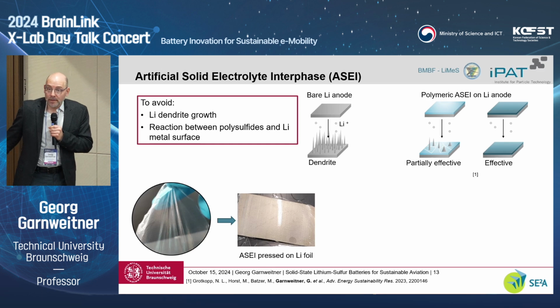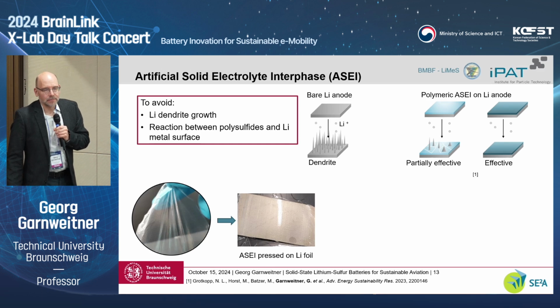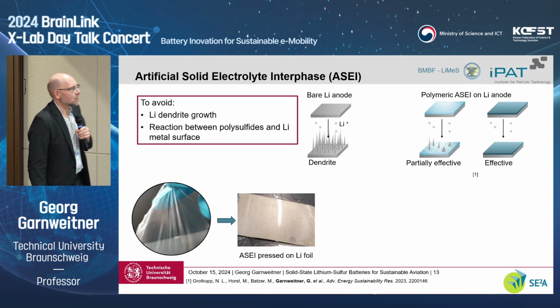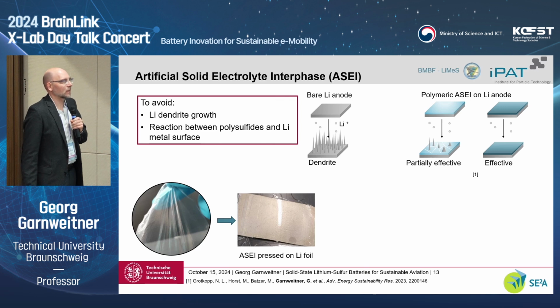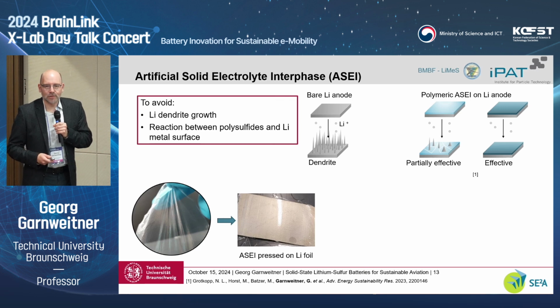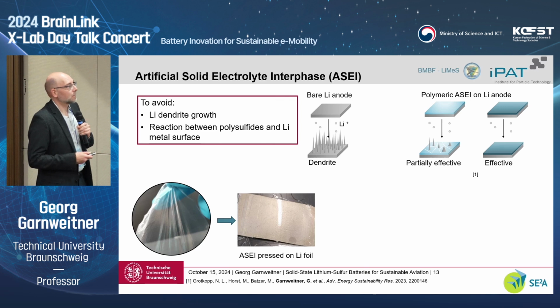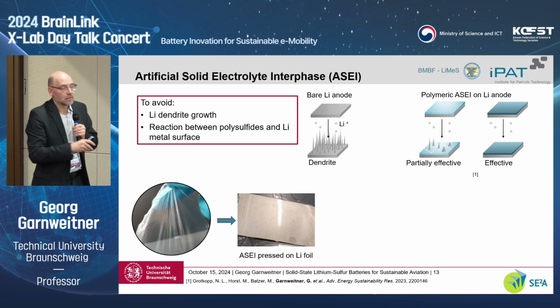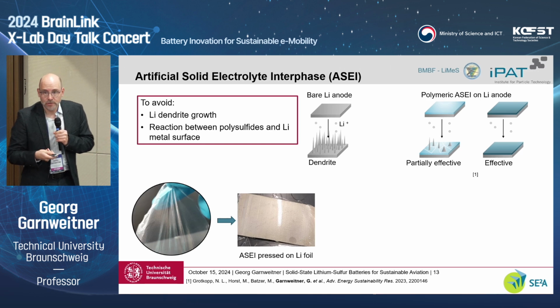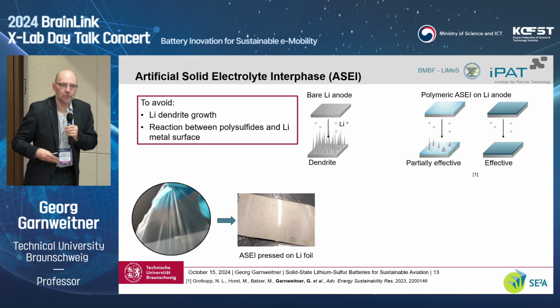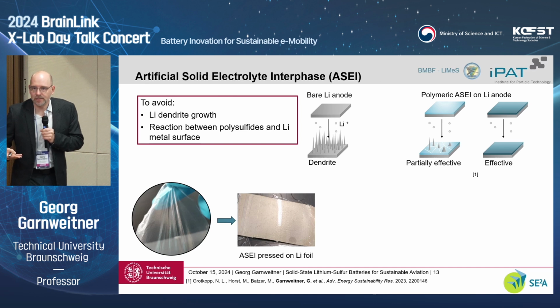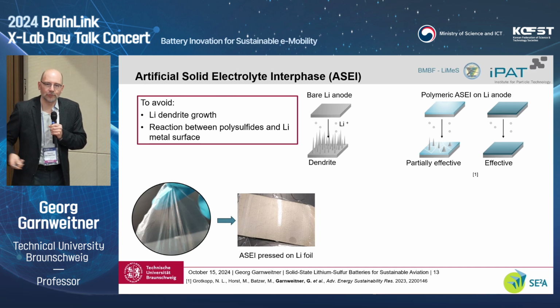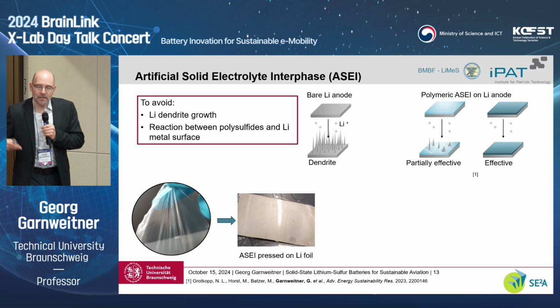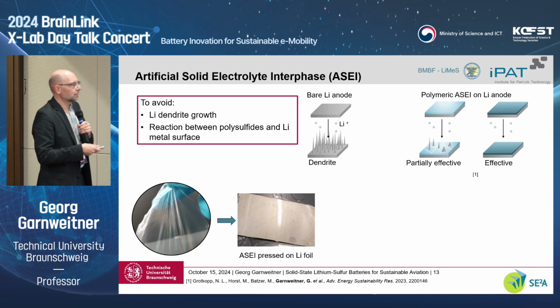So this is a problem, and well, what can we do about it? We have investigated a so-called artificial solid electrolyte interface. ASEI was already mentioned by Mauro, and here we basically have a layer. We focus on polymers that we work with, which of course have the advantage that they are flexible, and typically they can form a very good interface to the anode.